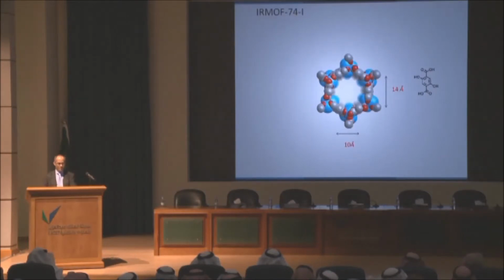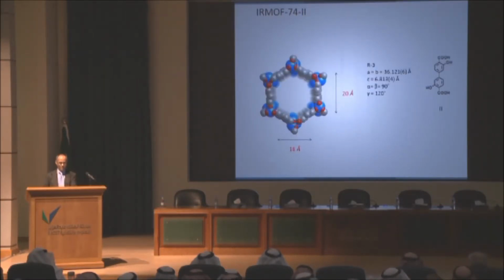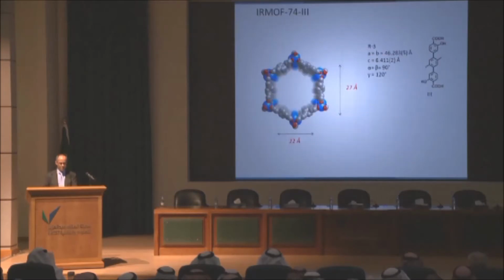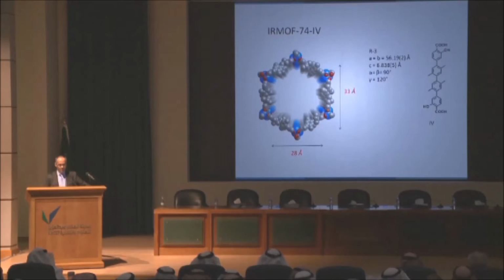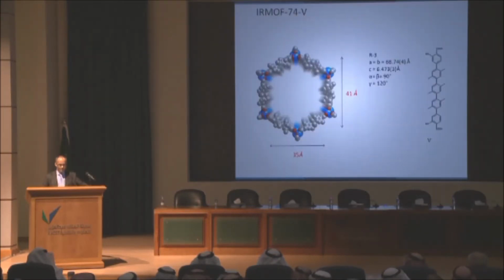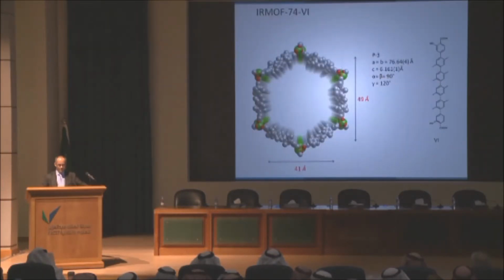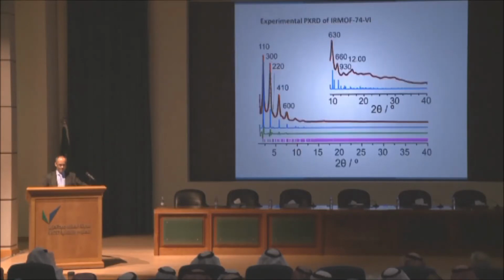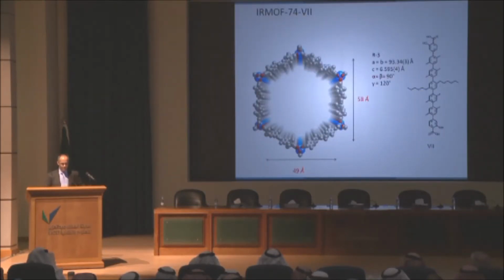And they're shown here. These are the openings of the parent structure, 14 angstroms by 10 angstroms. So with 2 phenylene units, you go to 20 angstroms by 16. To 3, you get 27 by 22. 4, 33 by 28. And this was essentially the previous record before we did this study. And so now you break the record with 5 phenylene units, 41 by 35. 6 phenylene units, 49 by 41, 7, 58 by 49.